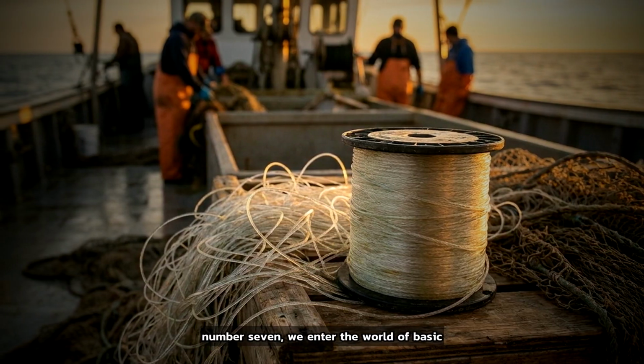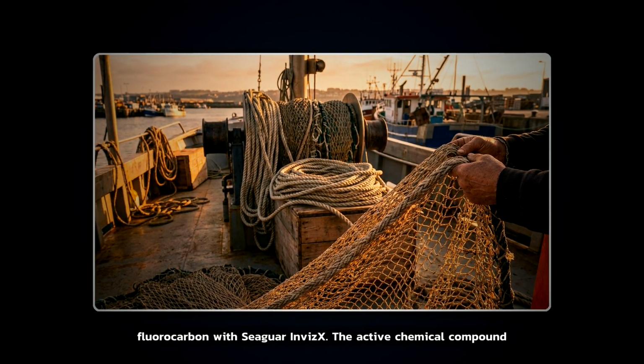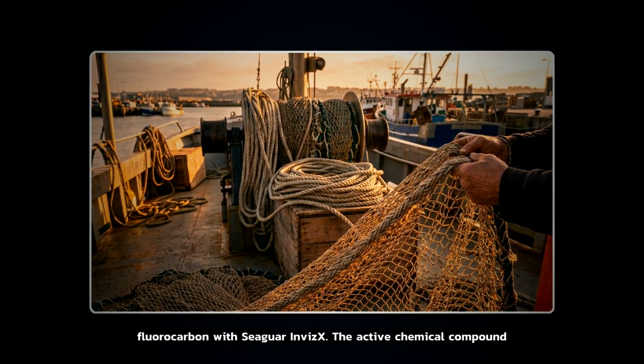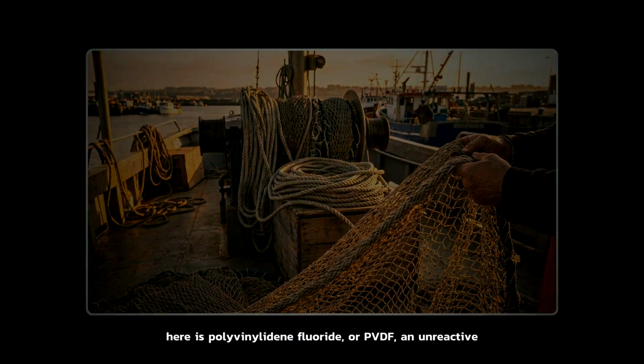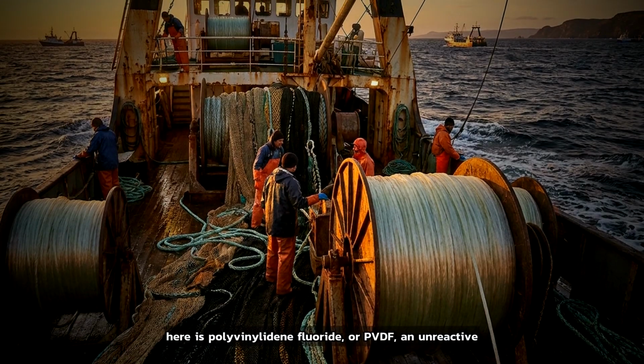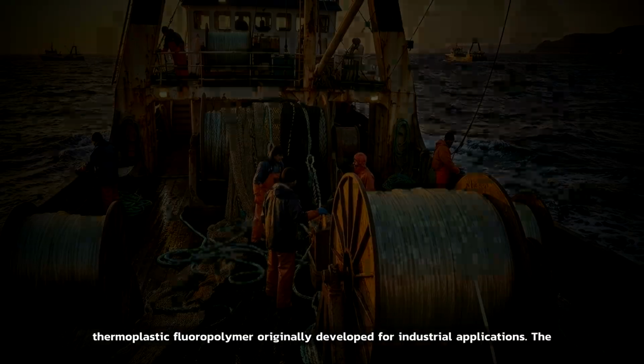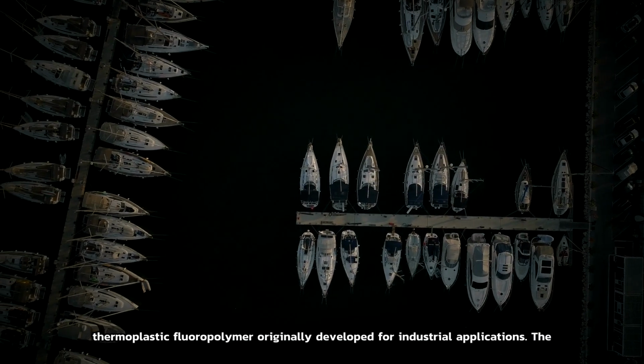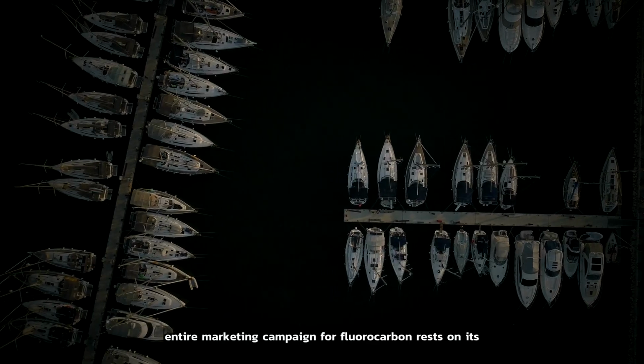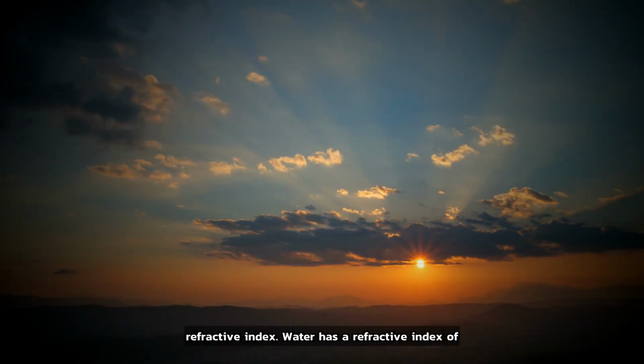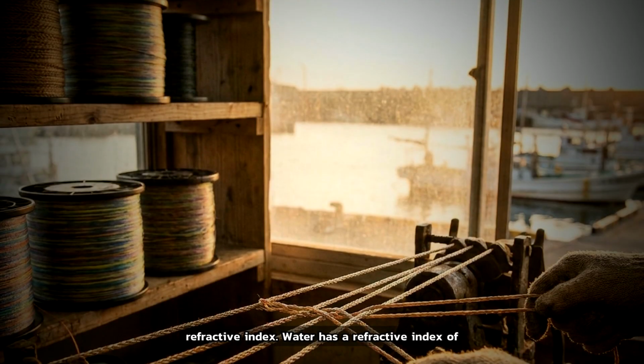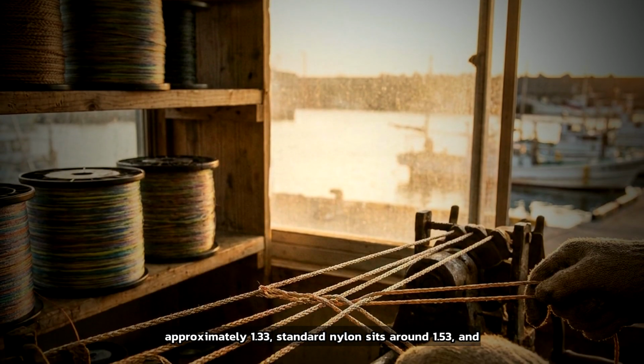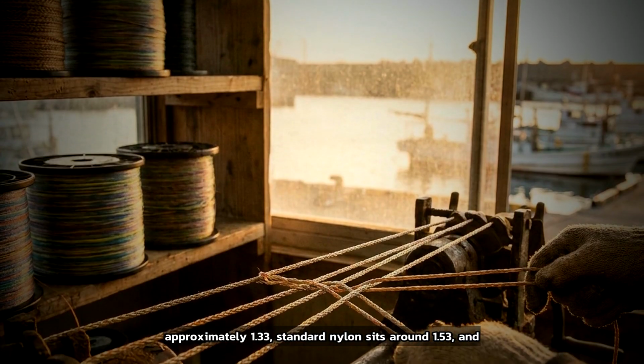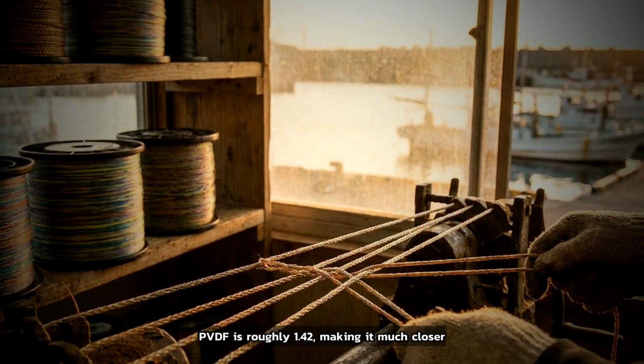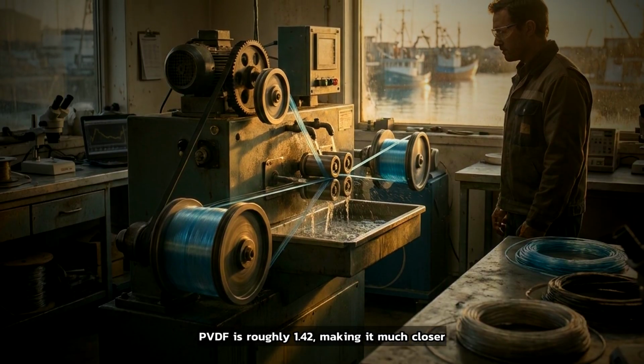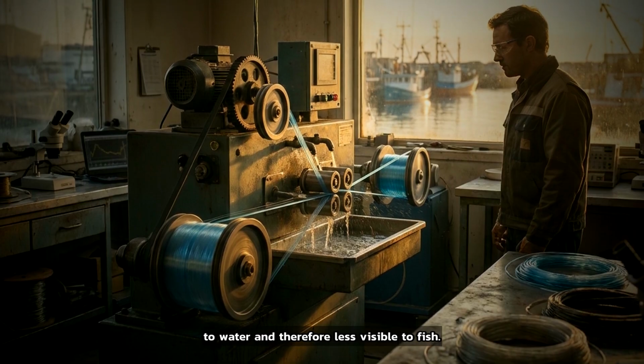Moving to number 7, we enter the world of basic fluorocarbon with Seaguar Invis X. The active chemical compound here is polyvinylidene fluoride, or PVDF, an unreactive thermoplastic fluoropolymer originally developed for industrial applications. The entire marketing campaign for fluorocarbon rests on its refractive index. Water has a refractive index of approximately 1.33, standard nylon sits around 1.53, and PVDF is roughly 1.42, making it much closer to water and therefore less visible to fish.